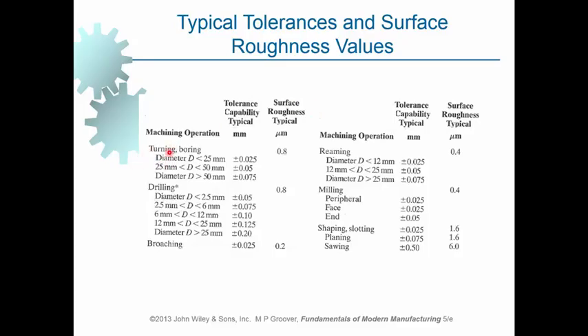For example, when we are making use of a lathe for turning operation, then we can achieve a surface roughness of 0.8 micrometer. And the resultant tolerance that can be achieved, depending on the dimensions of the cutting workpiece, is presented here. When the diameter of the workpiece is less than 25, we can achieve a tight tolerance of plus and minus 0.025 millimeter for the given dimension. As the diameter of the workpiece increases, the width of the tolerance region also increases. So we end up with a wider tolerance band for the acceptable parts.